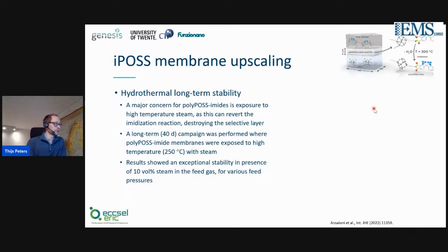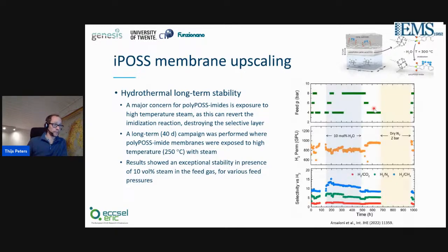So for that sake, we conducted a long-term test where membranes were tested at high temperature and high pressure, exposing them to different levels of high temperature steam, up to 250 degrees, up to 10%. And I won't go into details for the pictures here, but the results show that even within high temperature steam, up to 10 volume%, the membrane shows an exceptional stability. We basically do not see any decline in performance.